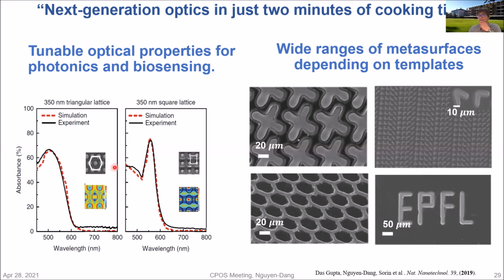So for example, in these simulations, I show you here two different types of lattice. Here we have the triangular lattice, and here we have the square lattice, and we have the same size of materials. By controlling the lattice, we can control the interactions between the particles, and then we can enhance absorption at a very specific wavelength. For example, here you have extremely high absorption with the square lattice.